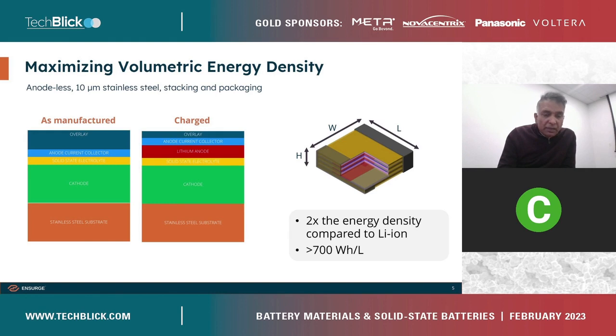We've been public about this, and as you'll see, there is no lithium that is pre-deposited. It goes straight onto the anode current collector, and then the packaging stacks above that. So this is one individual layer. The lithium is now generated on the first charge, and it is maintained there so that the battery is not over discharged. We discharge it down to 3 volts or so, and so we always maintain a seed layer of lithium.